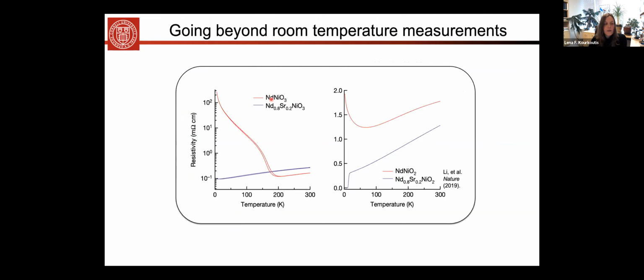This is the bulk phase, the 113 phase, and this is the superconducting phase. And all I want you to see from this is that here you have a material that goes through a phase transition. And that phase transition, this is actually a metal to insulator transition, happens well below room temperature. In fact, it happens around here, 180 or so Kelvin. Here on the right side, you actually see the resistivity, and it drops down to here. This is where the material actually becomes superconducting in the reduced phase.